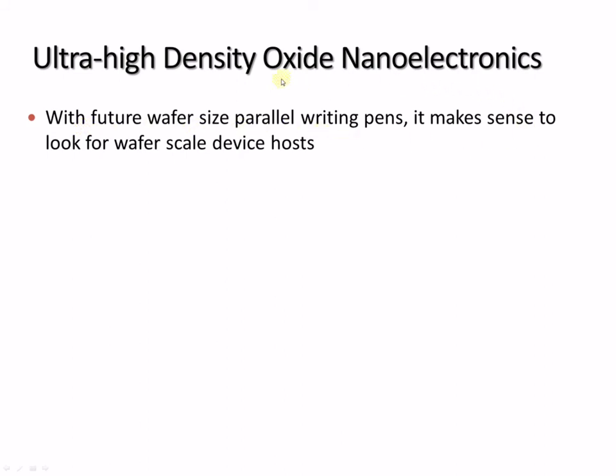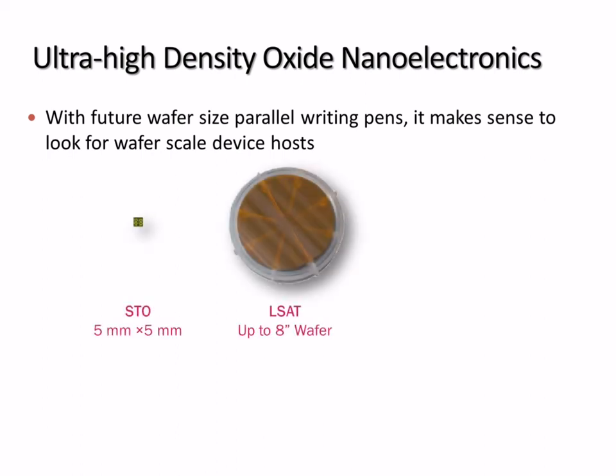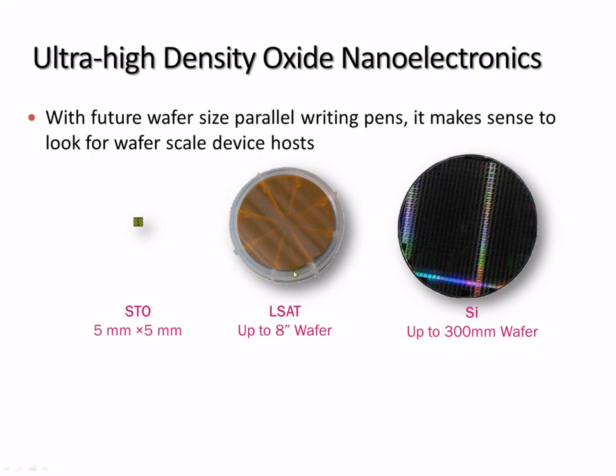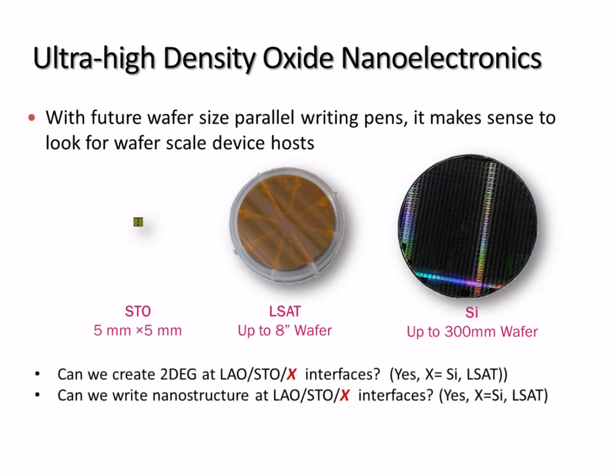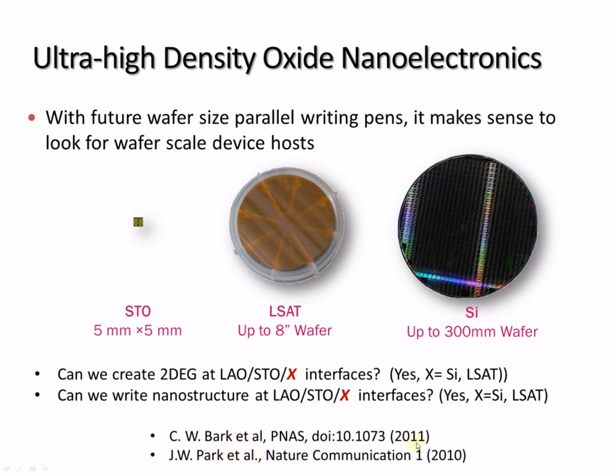For those of you who are experts in oxide nanoelectronics, you know that the strontium titanate substrates are notoriously unreliable. They're small, they're hard to work with. What you would like to have is some type of oxide wafer of comparable size to what you have for silicon. We've been working with both LSAT and silicon as a host carrier for growing strontium titanate. This is my collaborator Chang-Beom Eom, and with them we have been working to see if we can write nanostructures on the substrate. The idea would be to have lanthanum aluminate on strontium titanate on either LSAT or silicon. It turns out that we're able to do that for both of these, and there are publications describing both. Actually, our work of writing was presented at the March meeting, but was not in this publication.